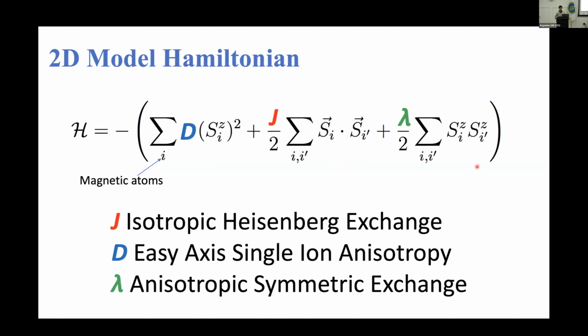From our energy-based calculations, we can determine these values, and we could use those values for things such as performing classical Monte Carlo simulations, or we can plug them into analytical models to estimate values like transition temperatures. Again, this Hamiltonian can have more involved terms, like DM interactions or Kitaev interactions, but for our cases, we just stuck to this simpler Hamiltonian for these magnets.